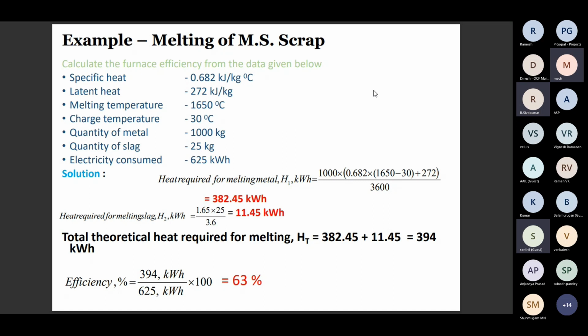Maybe you can collect it day wise, and day wise see how many melts you can take, and the entire value can be substituted. The total electricity consumed can be read from the energy meter installed in the furnace in a day. For example, in a day you can take 20 heats, so for the 20 heats, how much metal you have melted, what is the average temperature range, and what is the average slag rate generated. By applying this you can calculate your own furnace efficiency.